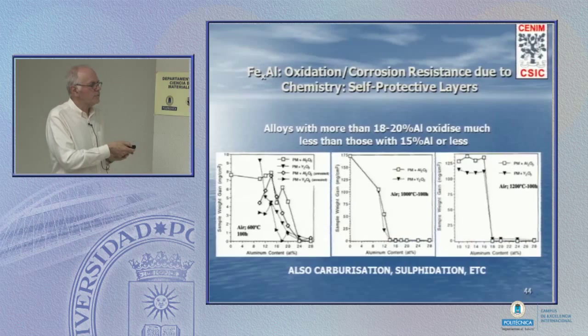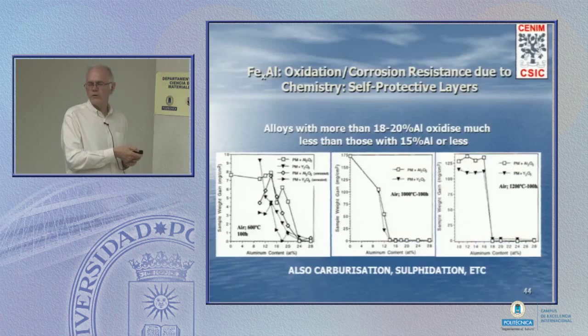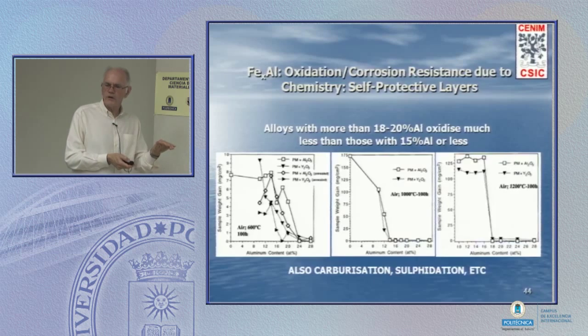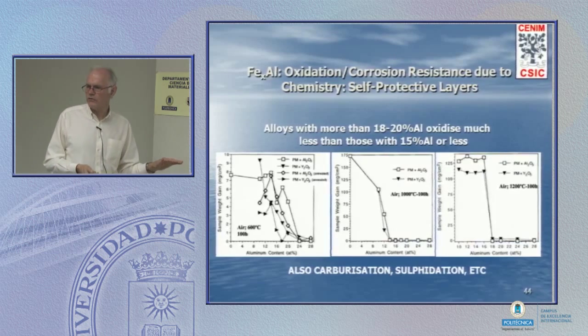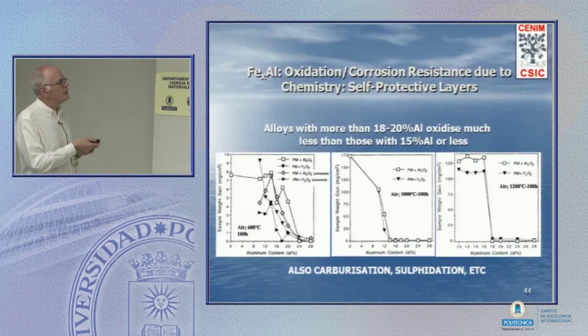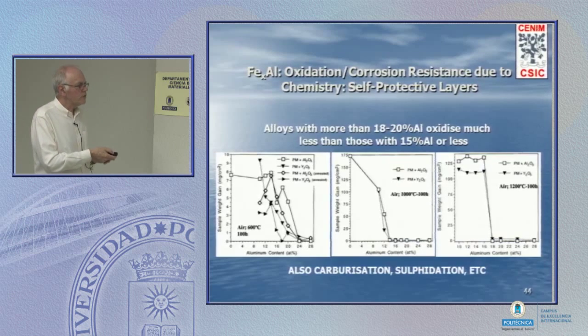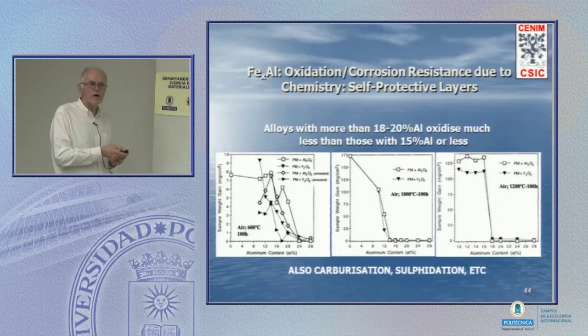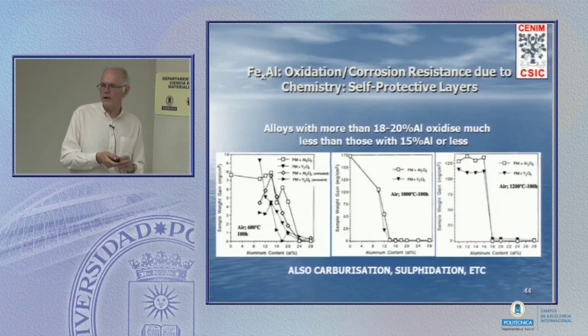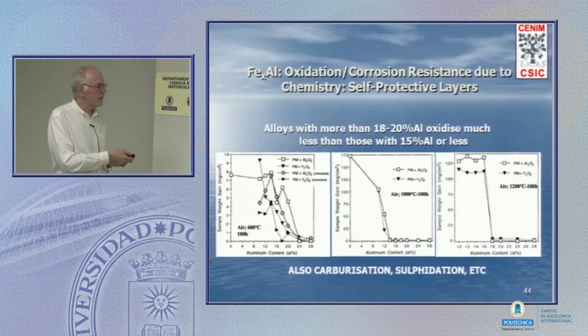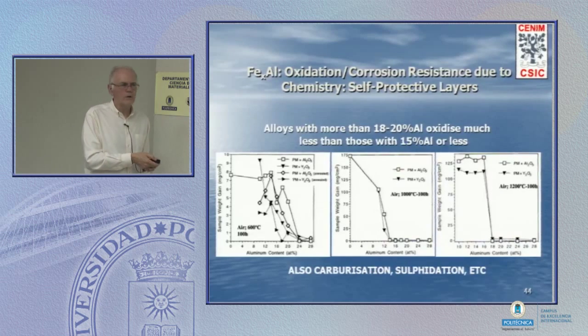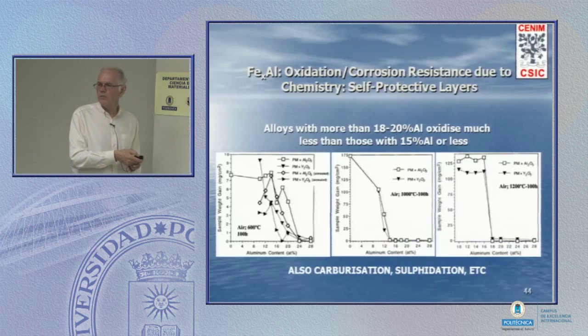When the aluminium content is below something like 12 or maybe 15%, there's this enormous oxidation. The moment you're above 15 or 20% of aluminium, then you form a thin oxide layer which sticks, protects, and that's the end of the story. And this alumina layer applies to oxidizing conditions, but also to carburizing and sulfidizing. And there are very many industrial environments in the petrochemical area, for example, where you've got a carbon excess, you've got a dirty sulfur-containing coal. And all these aluminides are absolutely wonderful. They simply sit there and laugh.